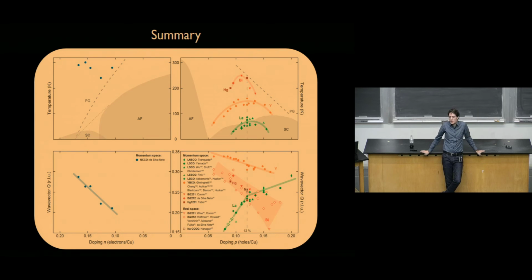But yeah. So for those stripe domains you showed, you look at the center of the sample. So what happens if you move your probe beams to the edges of the sample? Well, we haven't tried that, to be honest, but that measurement is a macroscopic measurement. So the footprint of the X-ray beam is of the order of 100 to 200 microns. So I don't know how big that edge would be, but if what defines that edge is something of the order of 10 nanometers from the actual physical edge of the sample, then we wouldn't even see that.